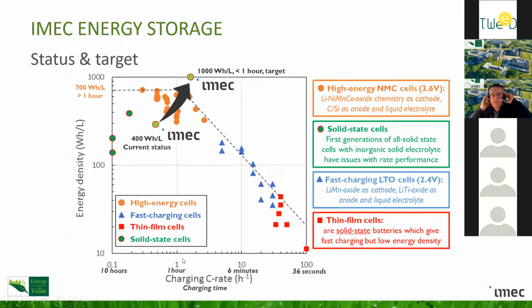So if you then compare with the different batteries that are out there, this is again the energy density on the left side. Let me put my pointer. Energy density on the left side, and then the charging rates. Of course, with very thin films, you have very fast charging, but very low energy density. And then you have other material concepts which can give you a bit slower charging but higher energy density. And the typical batteries used, like for cars at this moment, have this type of NMC material composition, which have charging in about 1 hour or a bit less, a bit more, depending on the type, up to this limit of 700 watt-hours per liter. Currently, with the solid-state batteries, we are here at this 400 watt-hours per liter at a little bit less than 1 hour charging. And we're moving in this direction here to really cross this boundary and being applicable for, for example, automotive and other types of storage and fast charging.